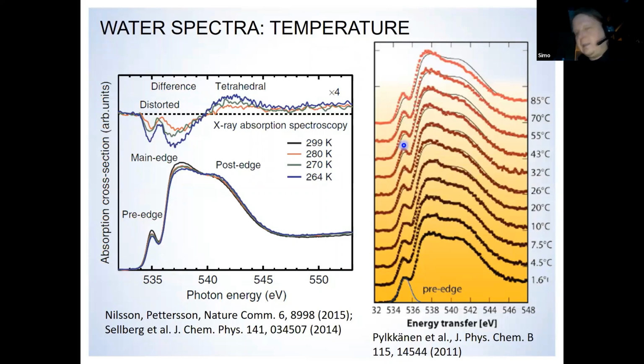And if you're working with an XAS spectra, one of the things that comes to mind is how to interpret these changes to the spectra. So we have two black boxes actually there. We could do a simulation of this spectra based on molecular dynamics simulations to get the structure and then calculate the spectra from the structure. But we don't know if the molecular dynamics simulations would deliver the correct structure of water, and then we don't know whether spectral calculations would give perfect agreement with the experiment. So there's a lot of research going on in interpreting the liquid water structure based on this.